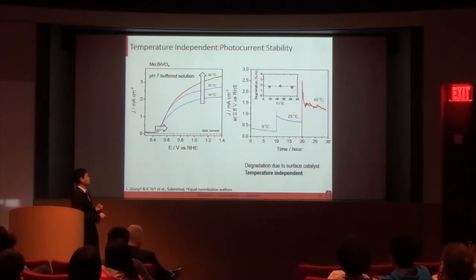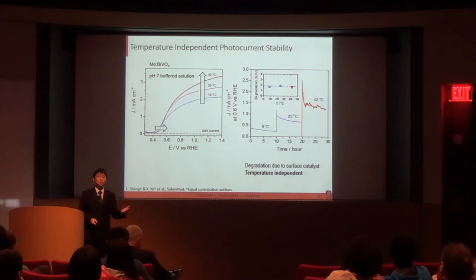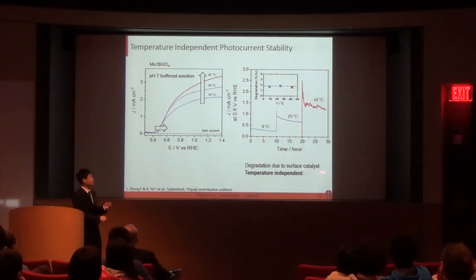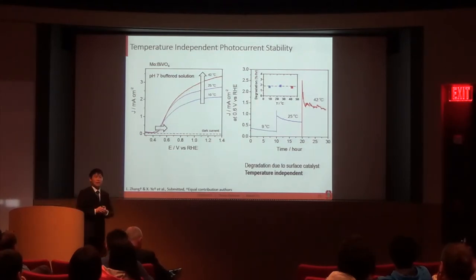And such a thermal enhancement is actually quite stable over a 30-hour stability measurement. The degradation is mainly due to the surface catalyst rather than the BVO by itself. And more importantly, the degradation is actually independent of temperature. So the next question is, how do we understand the mechanism behind the thermal enhancement?